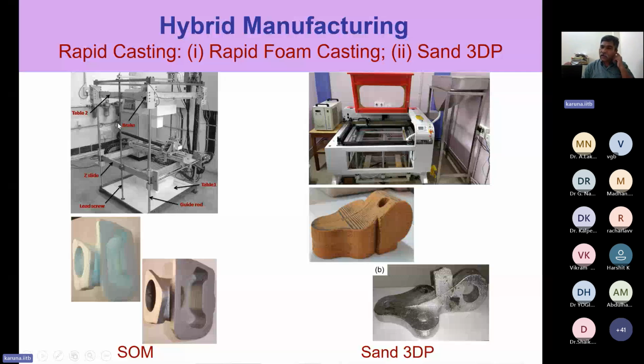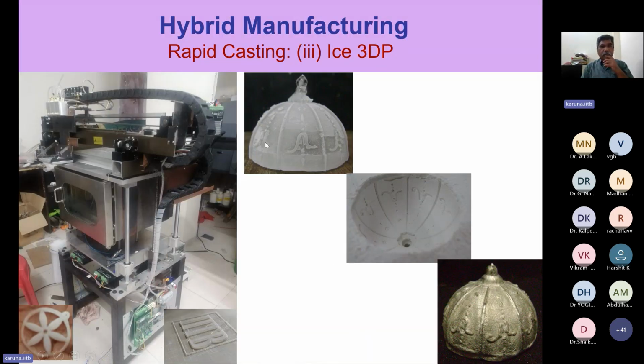Another machine which uses sand as the raw material builds molds like this. And this mold is for producing the casting like this. So this is our sand 3D printer. This is our ice 3D printer. So the first figure here is the ice pattern produced on this machine. Using this ice, using plaster of Paris as the mold material, we produce the mold. And remember, ice is at less than 0 degree centigrade. The plaster of Paris slurry will be at 15 or 20 degrees centigrade, even if you put it in the refrigerator to pre-cool it. So rather than absorbing the shape from the pattern, it will start giving heat to it and melt it, and the geometry will be ruined.